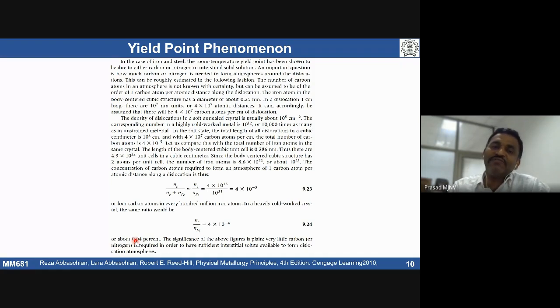So in that direction, what people do is add some carbide forming elements like titanium, boron, aluminum. In case of nitrogen, if I want aluminum nitride, it forms. With carbon, titanium carbide forms, or with boron, boron carbide, boron nitride. So those can avoid the formation of this yield point phenomenon in the material.